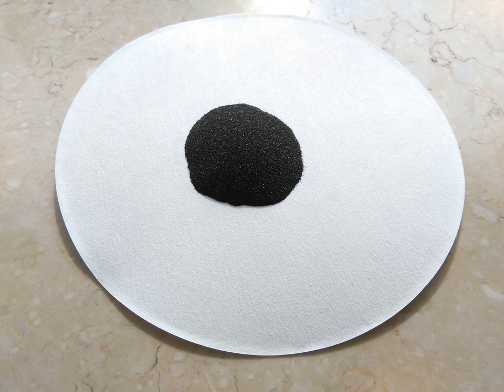When SiO gas is cooled rapidly, it condenses to form a brown, black polymeric glassy material, (SiO)n, which is available commercially and used to deposit films of SiO. Glassy (SiO)n is air and moisture sensitive. Its surface readily oxidizes in air at room temperature, giving a silicon oxide surface layer that protects the material from further oxidation. However, (SiO)n irreversibly disproportionates into silicon oxide and Si in a few hours between 400 and 800 degrees Celsius, and very rapidly between 1000 and 1440 degrees Celsius, although the reaction does not go to completion.